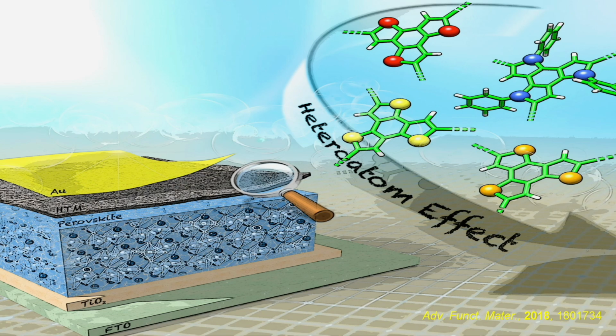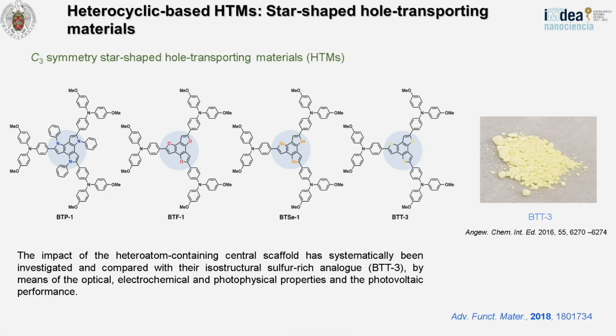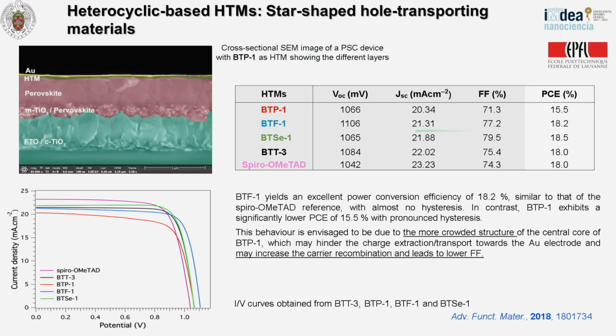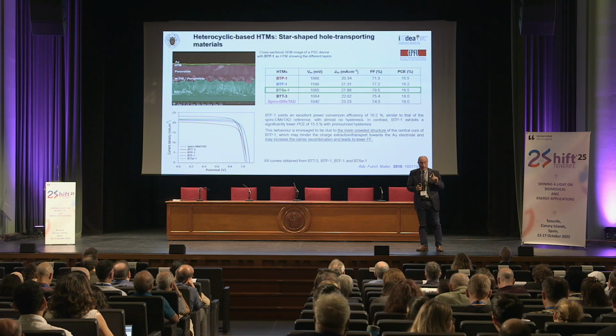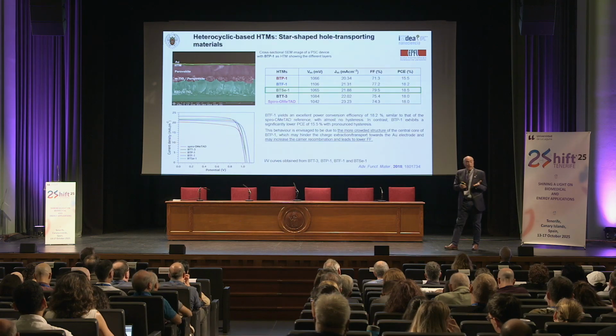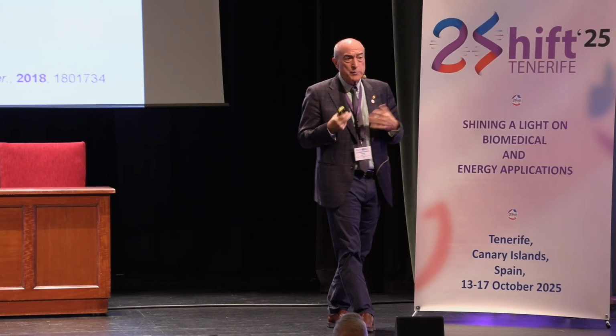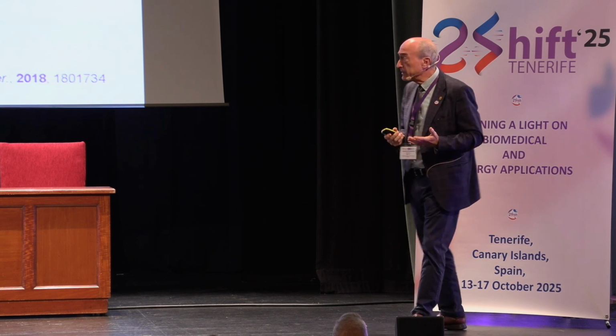And this was also published one year later, with nitrogen, oxygen, selenium, and sulfur. Without going very much into detail, you could see that all of them have the same behavior as spiro-OMeTAD. Some of you could say, then it's the same behavior. Yeah, but remember, spiro-OMeTAD is tremendously expensive. At that time, 1 gram of this material was around 500 euros. And it's difficult because you have to sublime. So this was not useful for practical purposes, for fabricating devices.